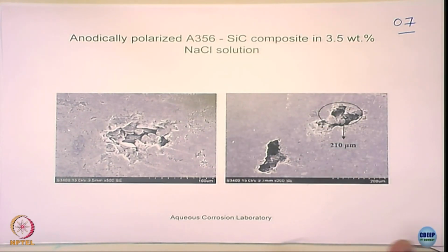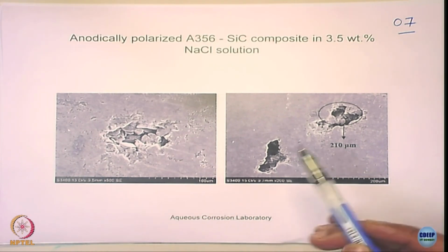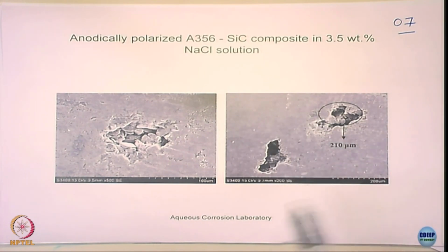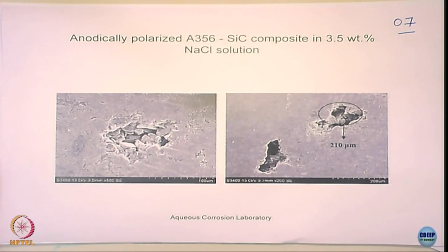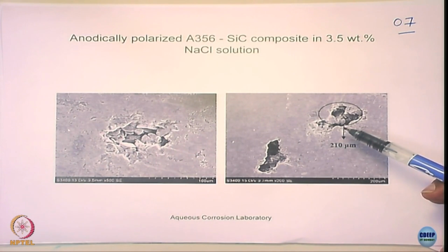This is essentially used for the rotor disc for automobile applications, the brake disc. It is normally made of cast iron, but cast irons are very high density, so they want to substitute with aluminum, but then aluminum suffers severe wear problems. So they add silicon carbide. The silicon carbide gives you good reinforcement and so better wear resistance.